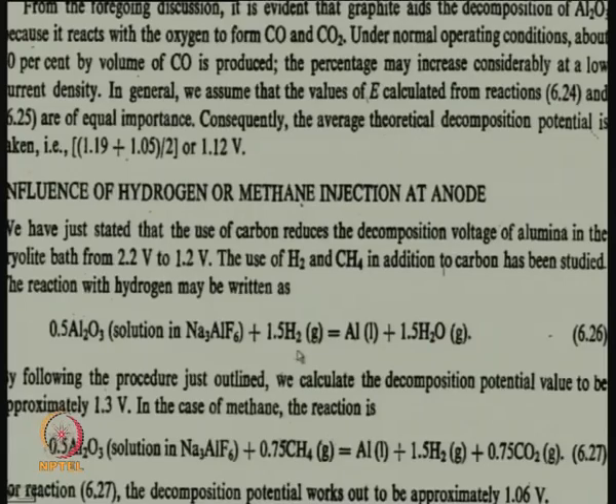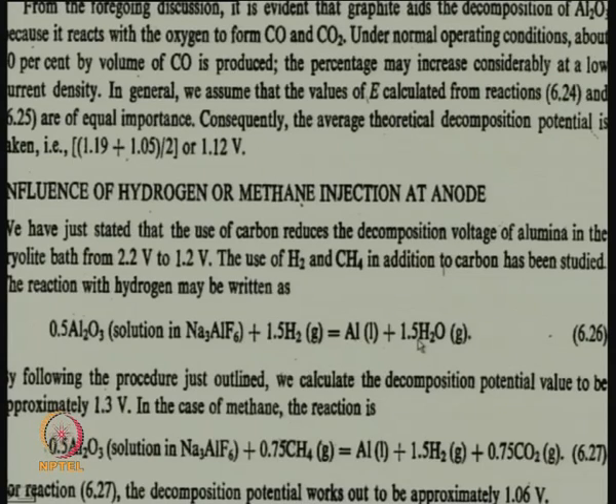Somebody has an idea: if the idea is to bring down the decomposition voltage by consuming the oxygen that is coming towards the anode, why can't we inject hydrogen near the anode? Let that oxygen ion react with hydrogen and just produce nice pure water. So your product would be water, of course in the form of steam, and you will produce aluminum as metal, and your graphite will be protected also. You will lower the consumption of graphite, because the bulk of the oxygen that is coming will react with this hydrogen. It is very good in theory.